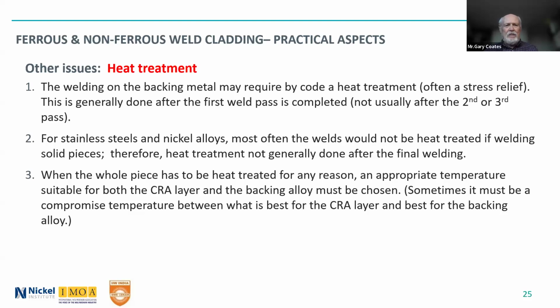And simply put, the stainless steel nickel alloys, you wouldn't normally heat treat them if you were welding solid pieces. So therefore, you don't need to do it after the final welding. For the stainless steel nickel alloys, you may need to do it for the backing material, the carbon, chromoly, whatever steel underneath. When you do have to do that on the whole piece, you have to choose an appropriate temperature suitable for both the corrosion resistant alloy layer and the backing material.